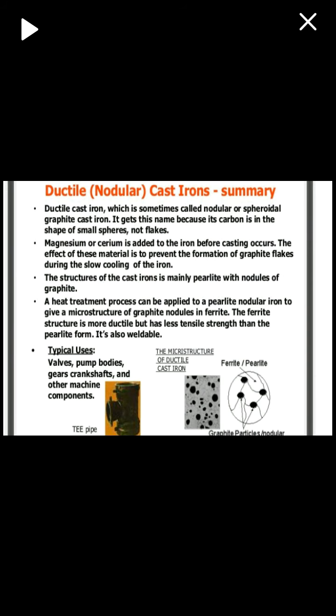Ductile nodular cast iron summary. Ductile cast iron, which is sometimes called nodular or spheroidal graphite cast iron, gets this name because its carbon is in the shape of small spheres, not flakes. Magnesium or cerium is added to the iron before casting occurs. The effect of these materials is to prevent the formation of graphite flakes during the slow cooling of iron. The structure of the cast iron is mainly pearlite with nodules of graphite. A heat treatment process can be applied to a pearlite nodular iron to give a microstructure of graphite nodules in ferrite. The ferrite structure is more ductile but has less tensile strength than the pearlite form. It's also weldable. Uses: valves, pump bodies, gears, crankshafts, and other machine components.